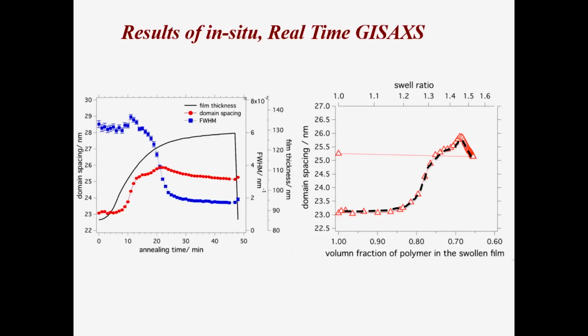And then you can go through and do an experiment where we look at the domain size, decrease, and then we have a problem. The problem that we have is that I can give you a film that has superb lateral order, close to being addressable. However, that's a film where I have solvent present, where I have this excess volume associated with the solvent, and the film is effectively above its glass transition temperature because I introduced the solvent to drop the Tg. Now, I've got to get the solvent out.